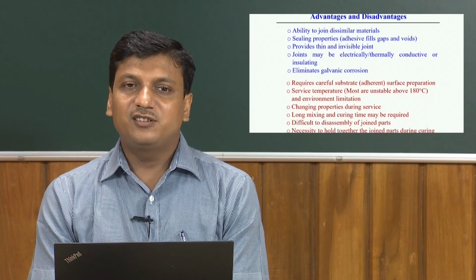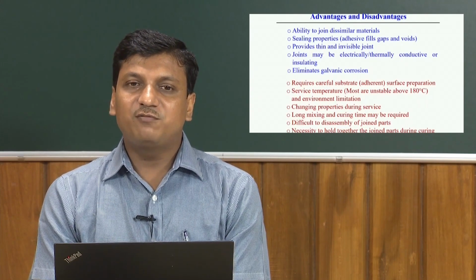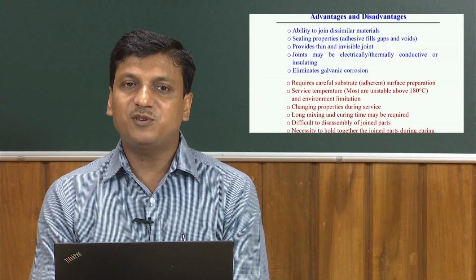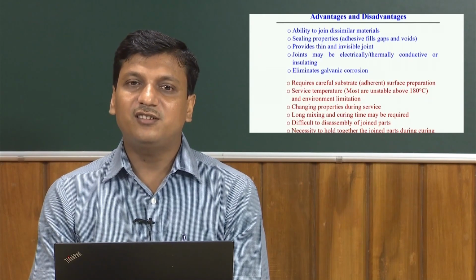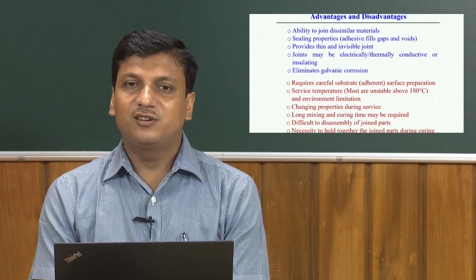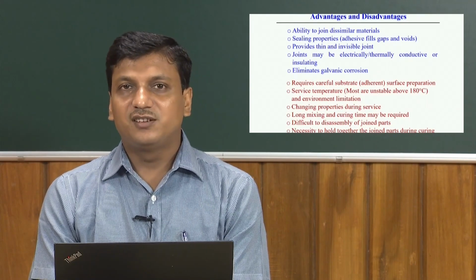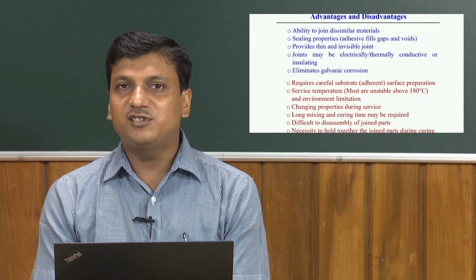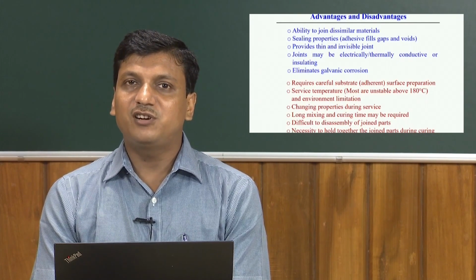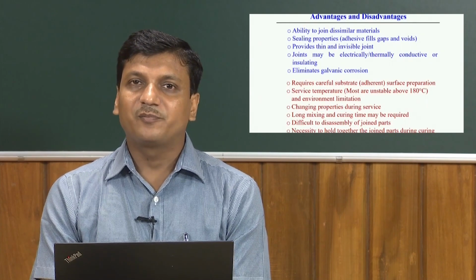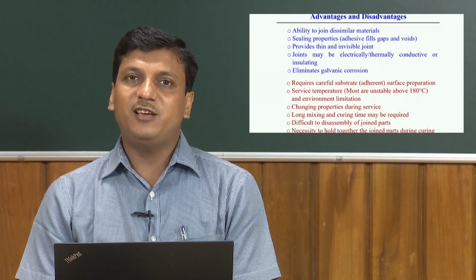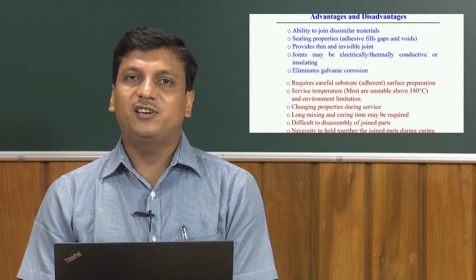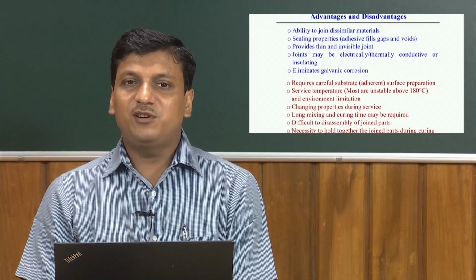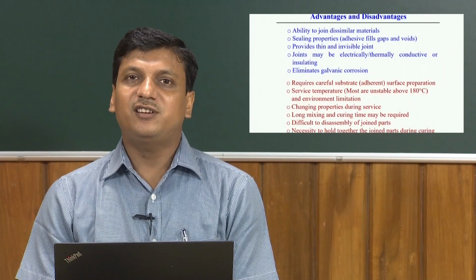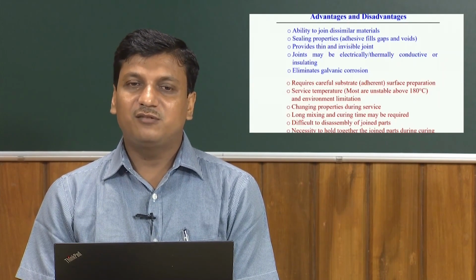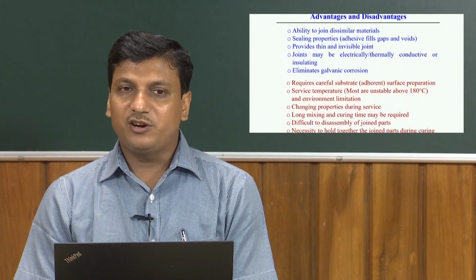But if we see the negative side, or maybe the disadvantages of adhesive bonding, the first is that it requires careful substrate surface preparation. Surface preparation is one important factor. One is the cleanliness and the roughness. These two are the important parameters for a successful joint using adhesive bonding. There is also a limitation on the service temperature, in most cases below 180 degrees centigrade, and also environment limitation. The environment also affects the service life of an adhesive joint, but the main limitation is the application temperature. Above 180 degrees centigrade the adhesive joint basically fails. So, that is the important limitation of this type of joining.